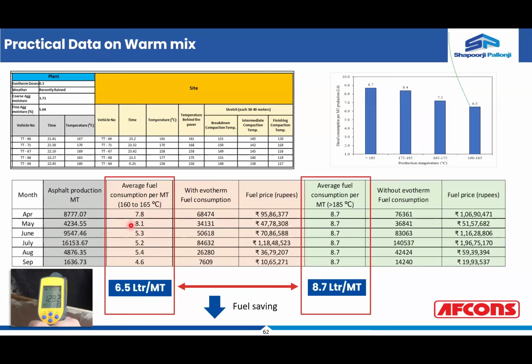Again, these values depend upon other factors like how the aggregates are being stored and how the aggregates are being introduced into the hot mix plant. In this particular case, the variation is mainly because of the moisture in the aggregate, because the aggregates are stored in open areas, and this is an area prone to high rainfall. Immediately after the rainfall, if you are using these aggregates, the maximum fuel is consumed to dry down the aggregate first, to the extent possible. But in such cases, the average diesel or fuel consumption to produce one metric ton of the warm mix was close to 6.5 liters, whereas in the case of hot mix asphalt under similar conditions, it is in the range of 8.7, and this 8.7 was arrived at as an average of 2 months' production earlier, in the initial phase when the warm mix asphalt was not fully established.